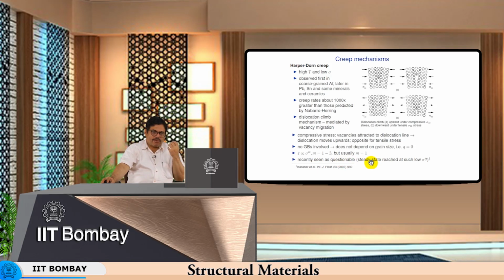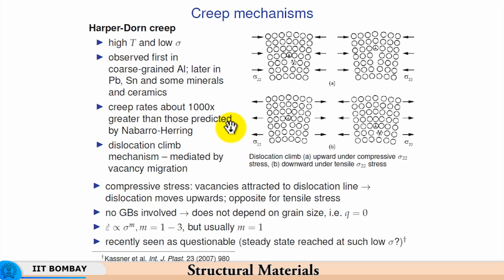Well, like many theories, you can have various opinions about it, but one can definitely say that when a number of mechanisms are operating in parallel, one can think of Nabarro-Herring creep. Also, in addition to that, the vacancies while diffusing through the grain can also aid dislocation climb, and therefore have a synergistic effect. So, the creep rate might not be explainable purely based on diffusion using the Nabarro-Herring mechanism. This Harper-Dorn creep mechanism could be aiding the increase in the strain rate for a given level of stress.